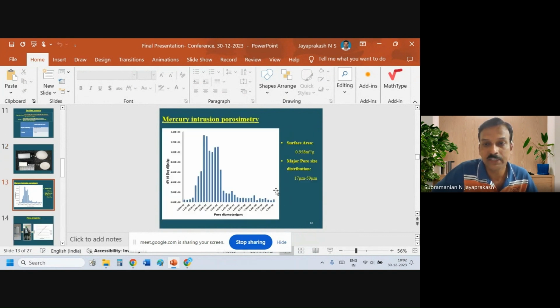So in order to study the pore size distribution, we did the mercury intrusion porosimetry method. By that method, we could find out the pore size distribution, and it ranged between 17 micrometer to 59 micrometer. And we found that the surface area was around 0.9 meter square per gram of this cryogel material.